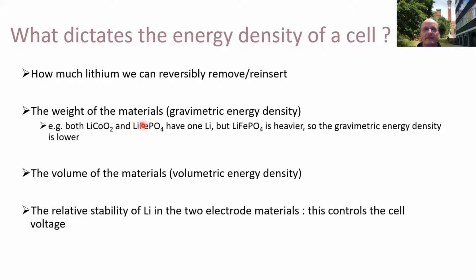The other thing that's important is the weight of your material, because again that relates to the energy. If you look at the literature, people will talk about gravimetric energy and volumetric energy. If I start with gravimetric energy density, this is essentially how much energy you have divided by the weight of the material. If we take two battery materials, this was the original, lithium cobalt oxide. This is a newer material, lithium iron phosphate. Tesla in particular are interested in this.